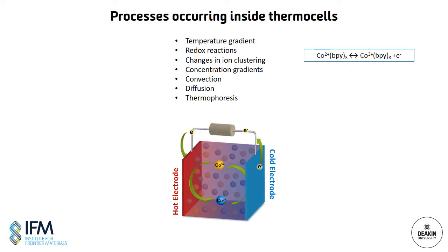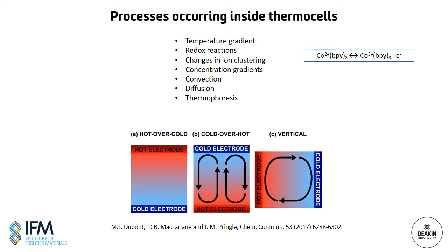Now, despite the simplicity of the concept, the processes that are occurring inside these devices when they're working can be extremely complex. So obviously you have the applied temperature gradient, you have redox reactions occurring at both electrodes, you have exchange of the counter anions between the two different types of cations. You're going to end up with spatially dependent concentrations of the two different redox species. And you may or may not have thermal convection occurring depending on the relative orientation of the thermal gradient with respect to gravity. So for example, if you have horizontal electrodes with a hot electrode at the top, you wouldn't expect any convection.